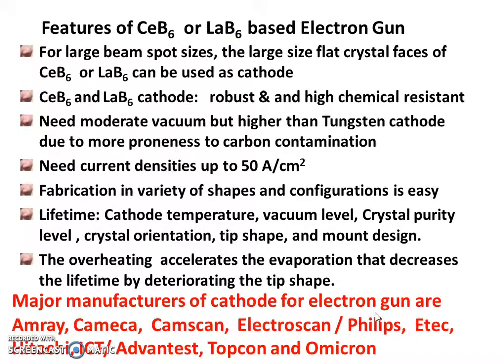The features of CeB6 and LaB6 based electron guns, you can say the comparative. For large beam spot sizes, the larger flat crystal faces of CeB6 and LaB6 can be used as a cathode. CeB6 and LaB6 cathodes are basically robust and they have very high chemical resistance. That's why they are used in SEM, where chemically active substances are also scanned. They need moderate vacuum, but higher than the tungsten cathode, due to more proneness to carbon contamination.